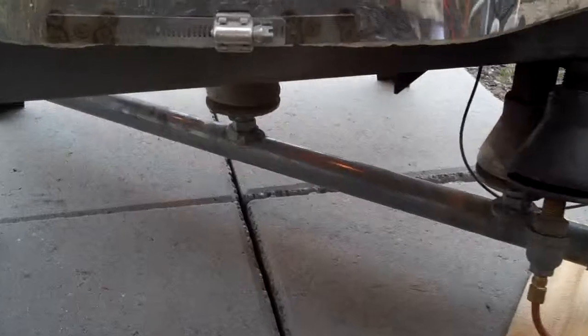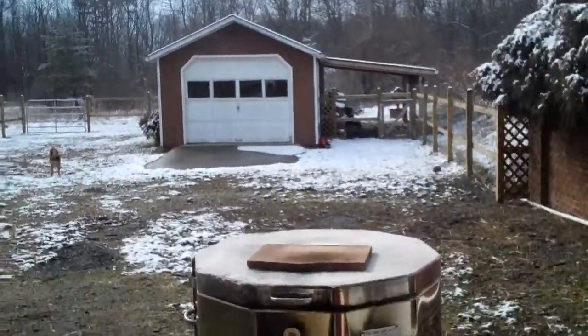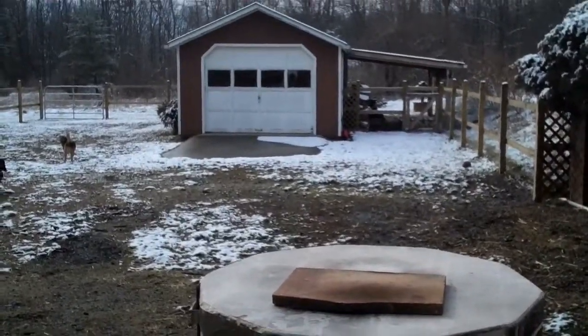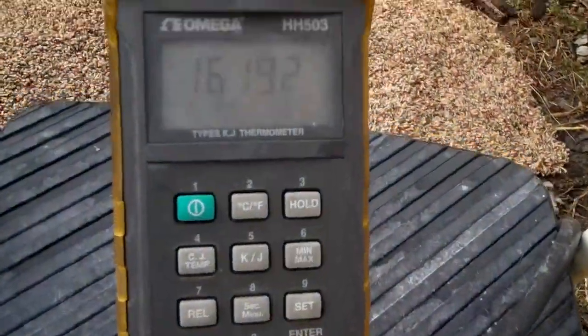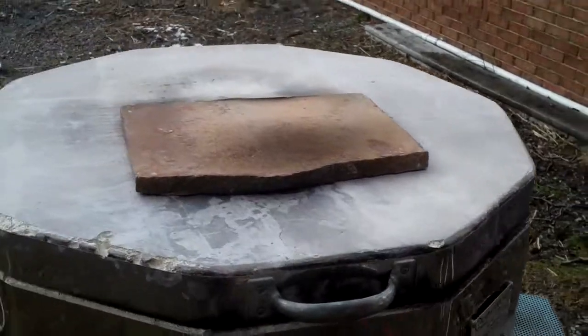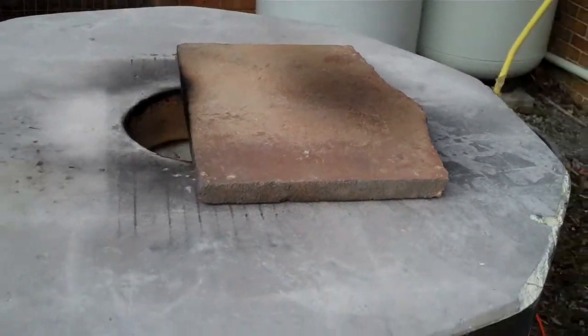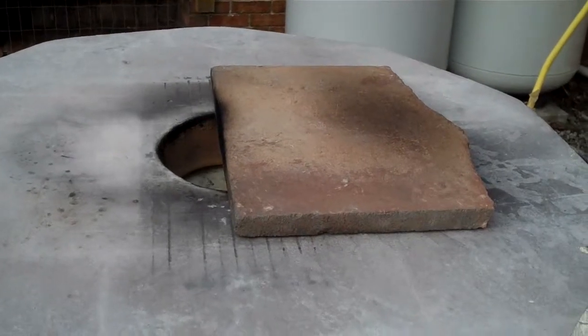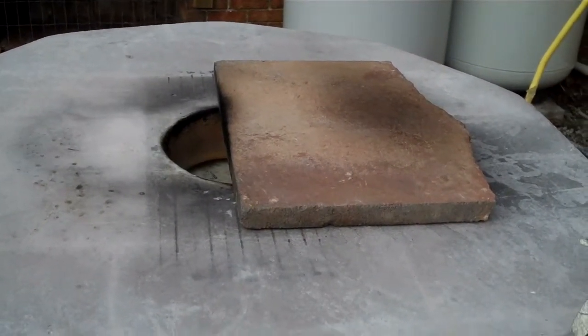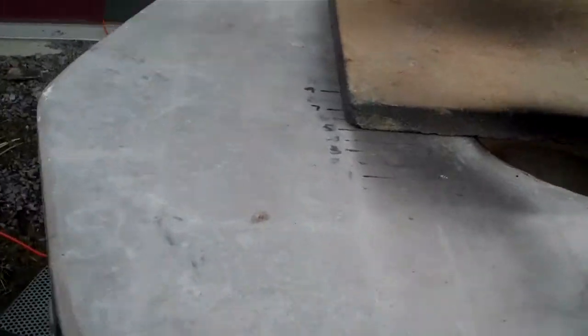We'll check back in later. Here we are, we're still firing the kiln, just got over 1600 degrees, so I am now starting my reduction. Here's the pyrometer. What I did is I slid this broken kiln shelf, which acts as my damper, over the opening in the lid. And based on the results of several past firings, I've been adjusting the amount that I close this thing, and I decided to close this one at number 5. You can see on the lid I've actually drawn some lines.